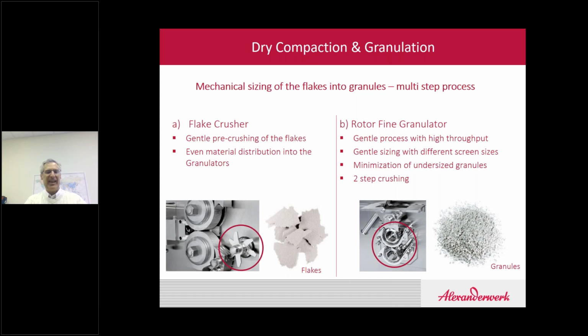And once those flakes exit the flake crusher area, it falls into a two-stage size reduction or granulation step. We call these the RFGs, or the rotary fine granulators. The way they work is the first granulator that the material sees will have a screen that's roughly, say, 3 or 3.15 millimeters. So that does your size reduction from the half-inch flakes that have been generated down to about 3 millimeters.